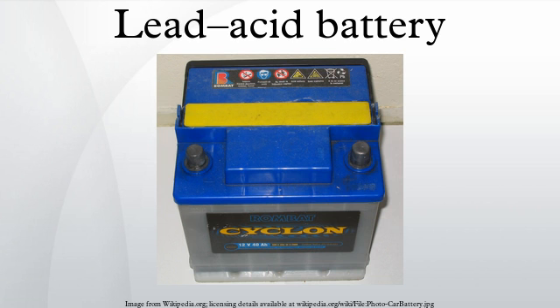Tin was added to lead-calcium cells to reduce the corrosion and open circuit effect. Tin helps to reduce this corrosion, but the benefit was deemed not worth $20 per pound, and many manufacturers dropped the tin. It is now rare to find antimony cells, with the exception of motive power.